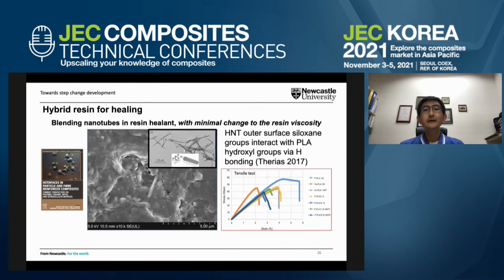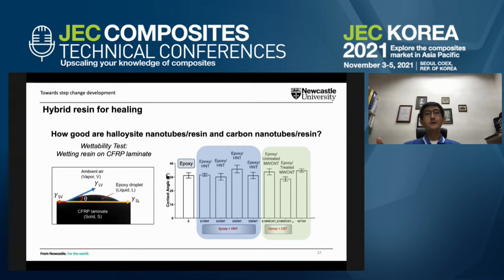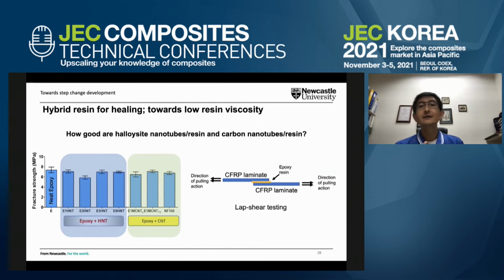So we looked at how we can blend the epoxy with nanoparticles, because we know that blending nanoparticles into epoxy, when it's hardened, will actually enhance the mechanical properties. And we have looked at halloysite nanotubes and carbon nanotubes. And we explored how, when we blend these nanoparticles into the resin, we looked at the wettability of these resins in order to establish the best concentration of nanoparticles that we should be using for each of these types. And we also looked at the strength of these resins when cured using lap shear tests.